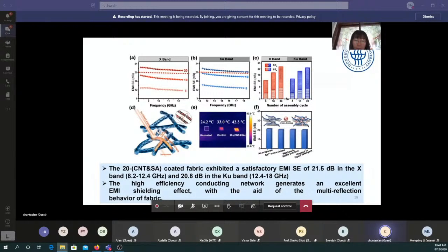This coated fabric has good EMI shielding efficiency, and after 20 assembly cycles, the fabric exhibits an EMI SE of 21.5 dB in the X band and 20.8 dB in the Ku band, which already meets the commercial requirement of EMI shielding fabric.